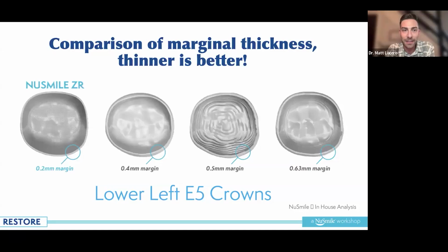The problem with that, at least theoretically, in my mind, when you think back again to biomaterials, is that with a zirconia restoration or any type of restoration, you want to have a uniform thickness. You don't want to have all of these changes and variations on the thickness of your restoration. Any of those thin areas are potential weak points where there can be a fracture. So in general, we want all of our restorations to be pretty uniform in thickness, and that injection molding technique really gives us that with the NuSmile ZRs.